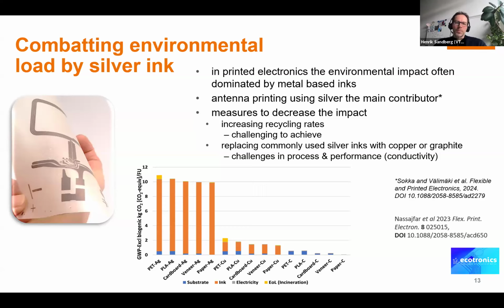Maybe use carbon-based inks for areas where you can have large areas to reach the required conductivity, and then you can use metal-based inks where you need, for example, fine features, narrow lines, and or a really high conductivity.